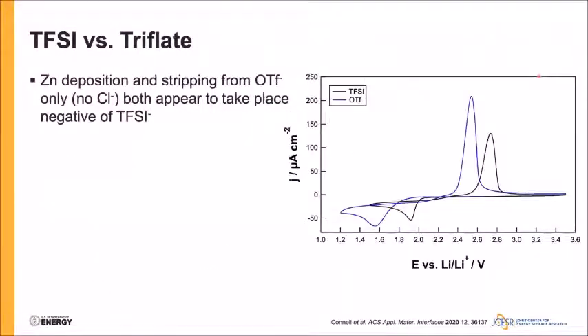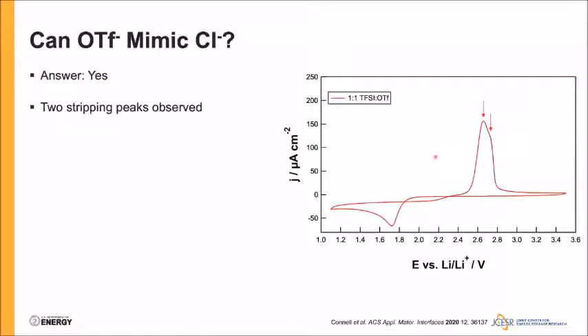And so if we compare the plating and stripping of just the 2 constituent electrolytes, so TFSI only in the black and triflate only in the blue, we see that the whole redox event appears to shift to lower overpotential, consistent with the higher association strength of the triflate anion. And so, to answer this question, can triflate be used to mimic chloride? We see the answer is actually yes.